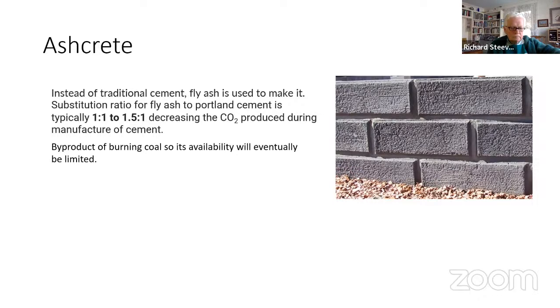I mentioned that fly ash in general, to be used in the process that produces Portland cement, needs to be amorphous. And fly ash that's been exposed to a lot of water and has then been allowed to settle over long periods of time can crystallize, and the silicate in that fly ash can crystallize, and that makes it unusable in that process.